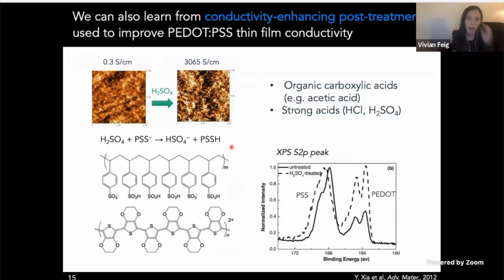And you can actually visualize this process using X-ray photoelectron spectroscopy, because there's a unique sulfur environment on PSS and on PEDOT, which means you can track the ratio of these two components. And so what people see is that after rinsing with these acidic solutions, because you've liberated some of that PSS from its attraction to PEDOT, you can remove some of it through rinsing, and you get a relative increase in the PEDOT to PSS ratio.